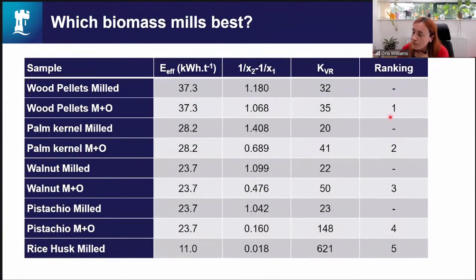So when we look at using von Rittinger, we can take the energy and the particle size reduction ratio to give us a specific von Rittinger rating for each material. And what you see is that it gives you a combined metric. Some materials might not have a huge energy consumption like the walnut, but its particle size reduction wasn't very good either, so that influences its ranking. And we could see that if we just looked at the product of the milling process, we get different results than if we combine it with the overflow.